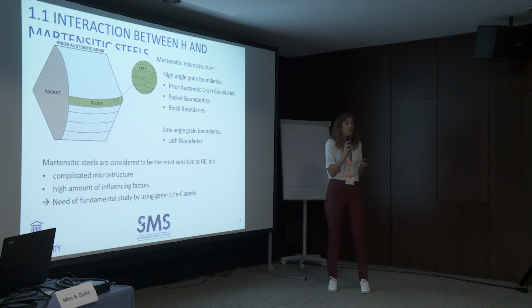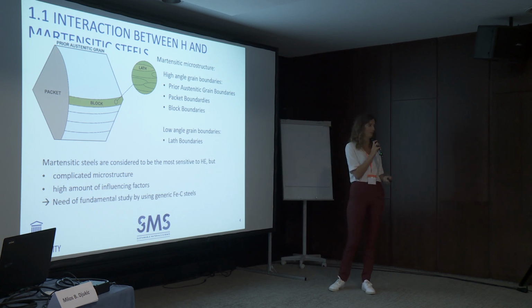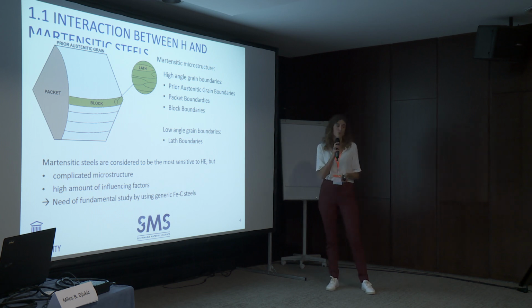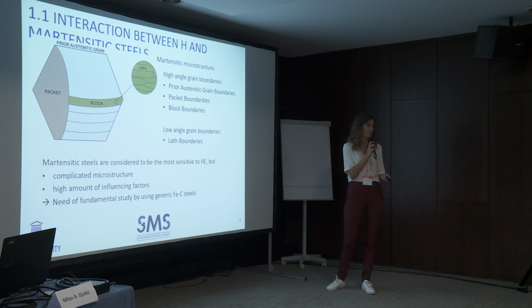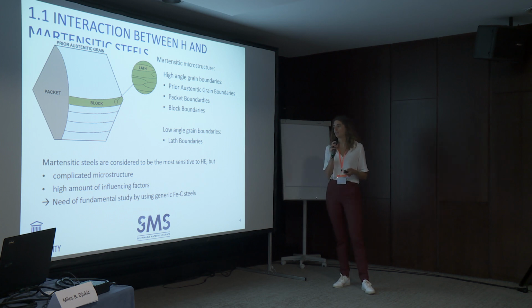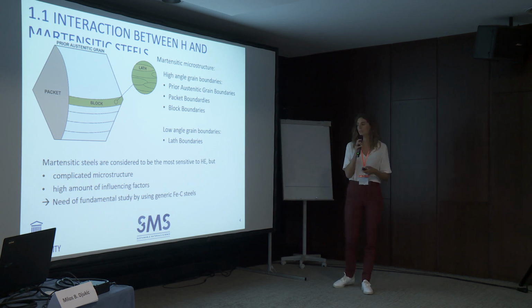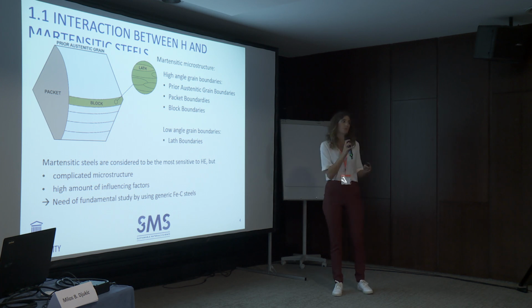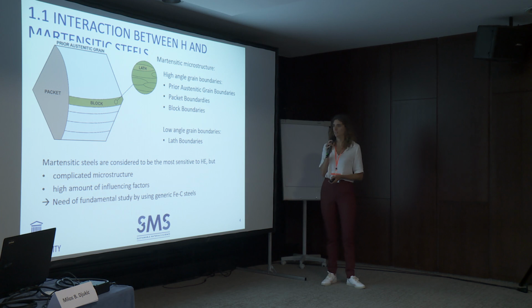These very complicated structures hinder, in fact, the complete understanding of the hydrogen embrittlement mechanism. Moreover, it also has a high amount of influencing factors, such as carbides, precipitates, second phases, segregations, and so on. And therefore, during my PhD, I used generic iron carbon steels with a simplified structure to get more fundamental insights on the interaction between hydrogen and martensitic steels.